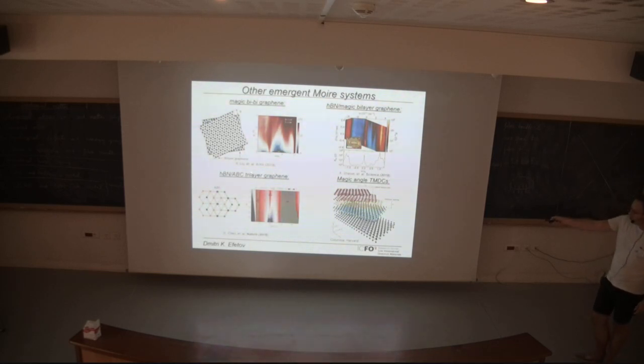Then another recent effort was in hBN-aligned ABC trilayer graphene. This is now not AB. This is trilayer graphene where, similar to AB bilayer graphene, three layers of graphene are on top of one another in this ABC type of stacking order. If you again align it with hBN and create a Moiré lattice, you can also get correlated states and superconductivity. So somehow, surprisingly, this picture of flat bands and interactions giving rise to correlated states and superconductivity seems to be universal across many different systems.